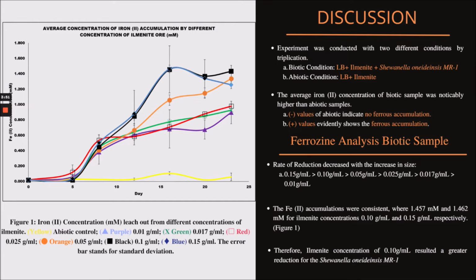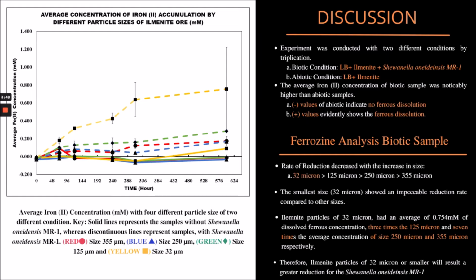The results were similar and matched each other, proving that 0.10 gram per ml was the optimum concentration for the maximum iron leaching. Moving to figure 2, here we have manipulated the particle sizes. The largest size was the 355 micron, which is the red line, and the smallest was the 32 micron, which is the dotted yellow line. Looking at the graph, the differences are very noticeable: the leaching was highest in the 32 micron ilmenite treated with Shewanella oneidensis MR1. Iron accumulation was recorded at 0.754 millimolar, which was 7 times that of the 355 microns. Therefore, ilmenite particles of 32 microns or smaller will result in a greater reduction by Shewanella oneidensis MR1.